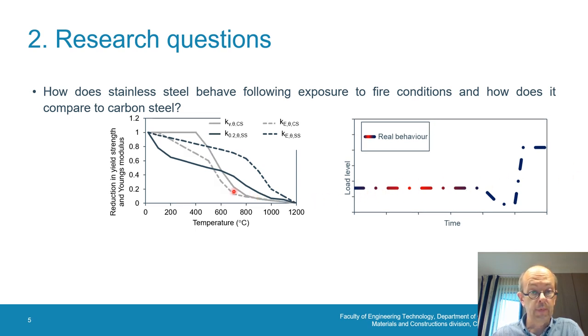Looking to carbon steel, we see that carbon steel can maintain its yield strength to a temperature of about 400 degrees Celsius, but then it is rapidly decreasing, and at a temperature of about 650 degrees Celsius, both curves are switching. It means that above 650 degrees Celsius, the capacity of stainless steel in yield or proof strength is much higher than the one of carbon steel. Also, the elastic modulus is superior to the one of carbon steel.